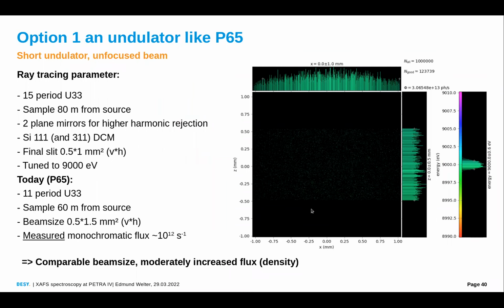The simple matter of fact is that a bending magnet, oh, sorry, I confused this. The option one is to use the undulator like we did at PETRA III. So this is the example which I'm showing here. Sorry for the confusion. This would work if we use a similar undulator like the one we have. In this case, I calculated with 15 periods. We would end up with a maximum flux of the order of 10 to the 12, 10 to the 13 photons per second. So it's certainly possible to do the same things that we did at P65. So this is an option which we need to keep in mind in case the other options don't work.